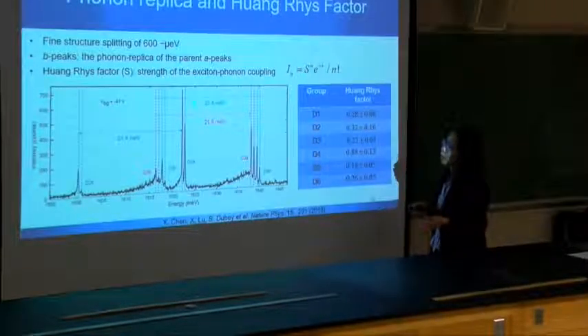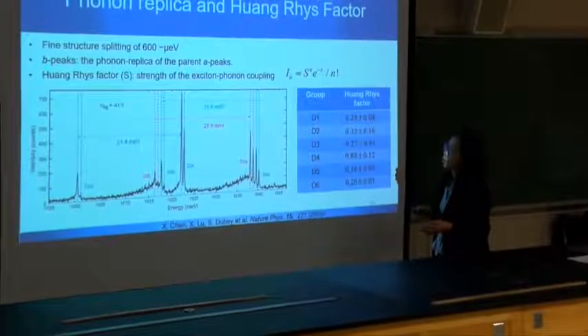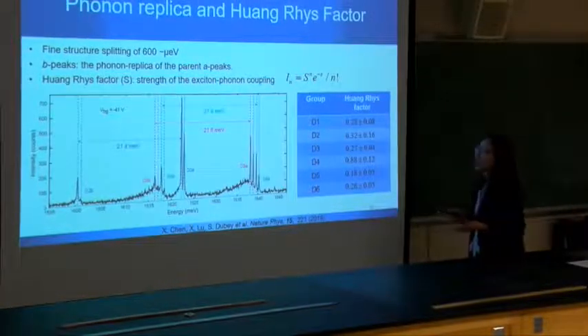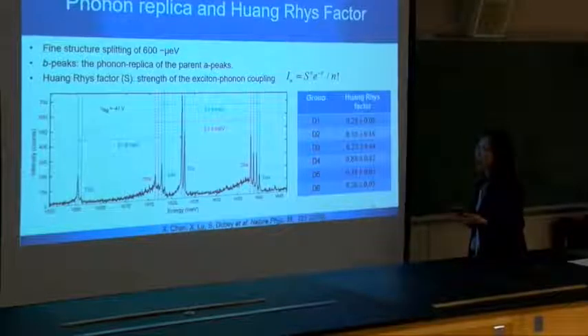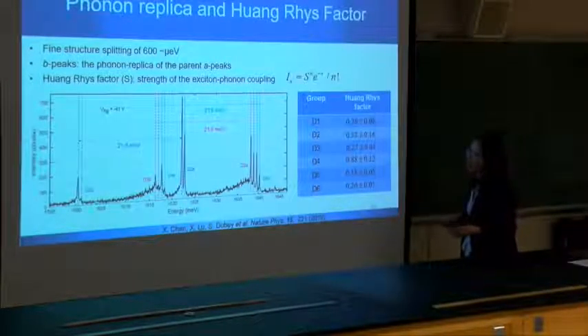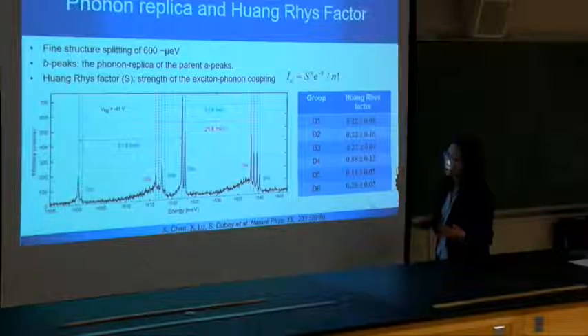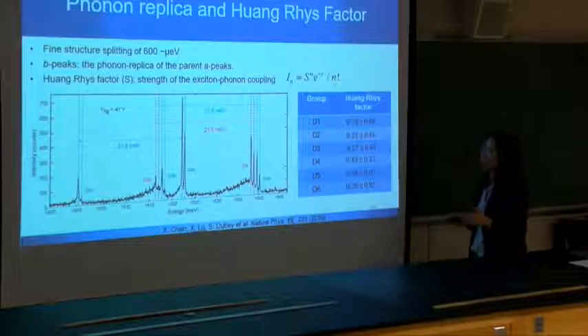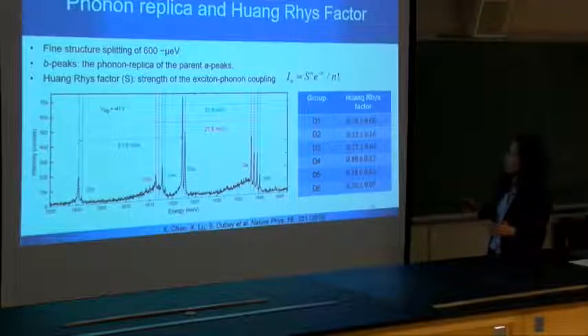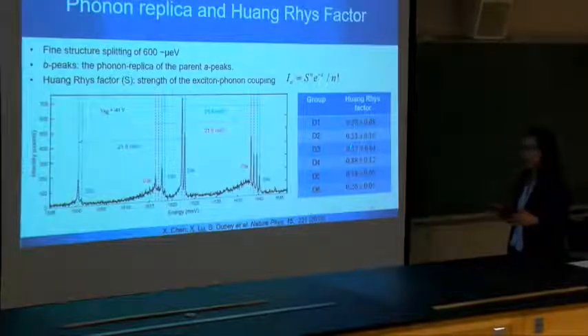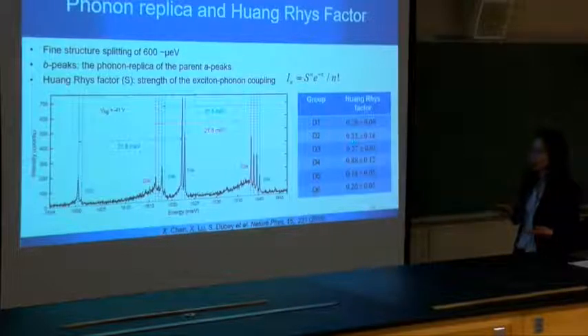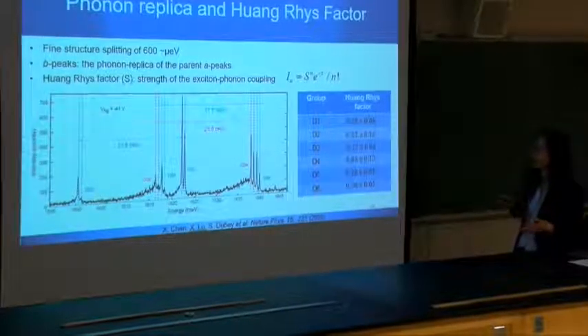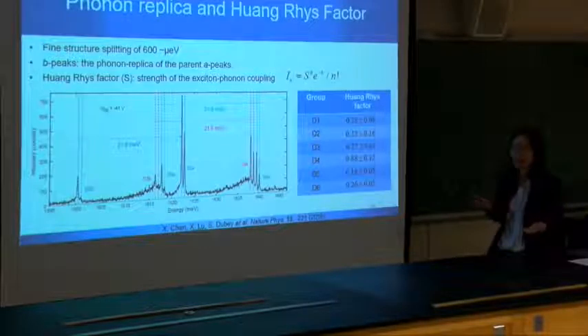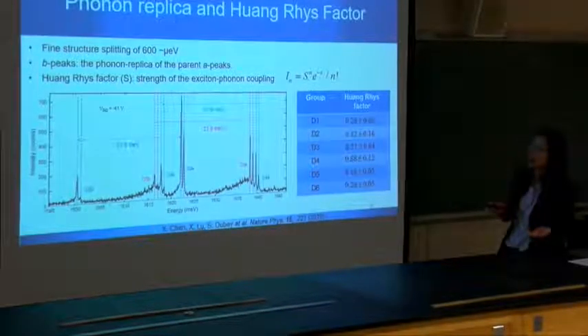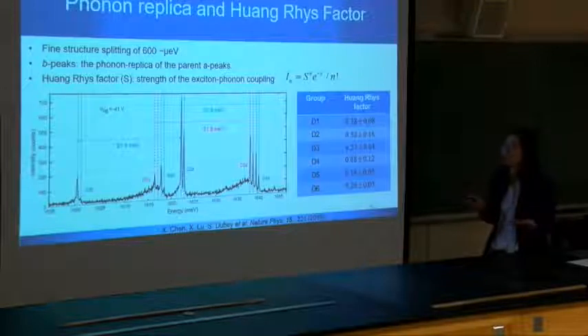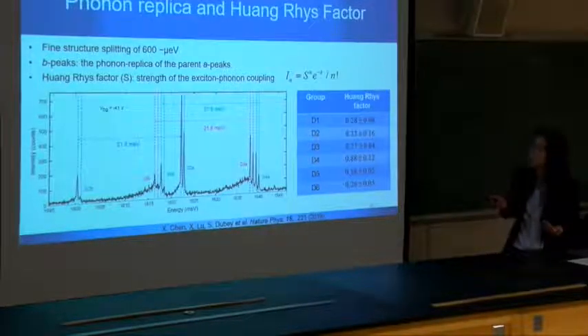And for a phonon replica, one important parameter is the Huang-Rhys factor. It's a measure used to quantify exciton-phonon coupling. So we extract the intensity of the phonon replica and compare it to the parent peak, the A peak. And this is the Huang-Rhys factor we extract, for most quantum dot groups around 0.3. It sounds small, but it's also one order of magnitude larger than for gallium arsenide quantum dots, which means that the exciton-phonon coupling in this transition metal dichalcogenide system is pretty strong.